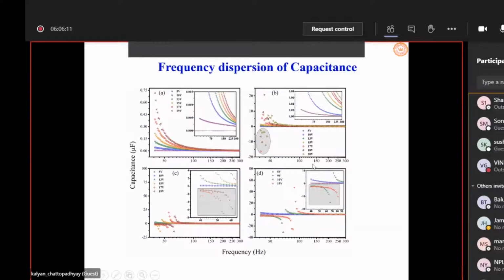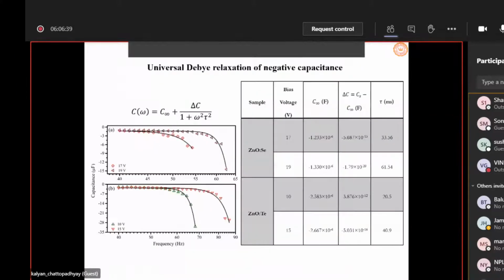Then it switches back to the positive part. And this effect is more prominent in case of selenium and tellurium doping. You see here, it starts from here, comes negative and then jumps and then follows again normal dispersion. So this is repeated, and if you think that these data are not scattered, in case of selenium and tellurium, you see that it follows some definite relaxation process, and you can fit this equation with universal Debye relaxation here and find out the relaxation process.